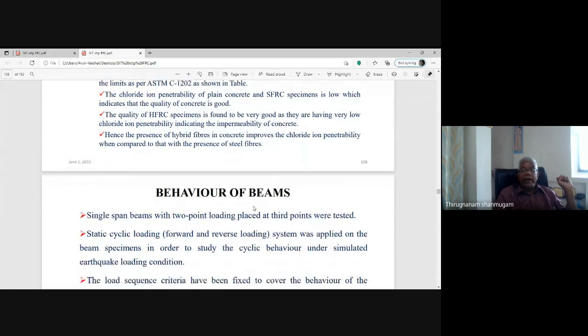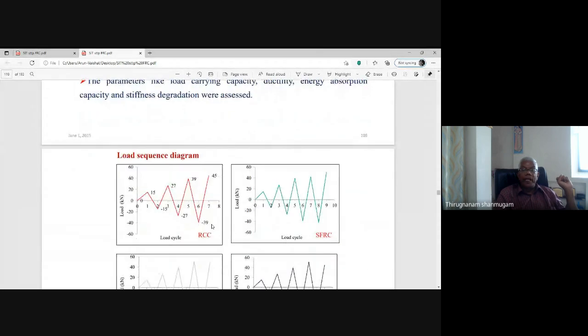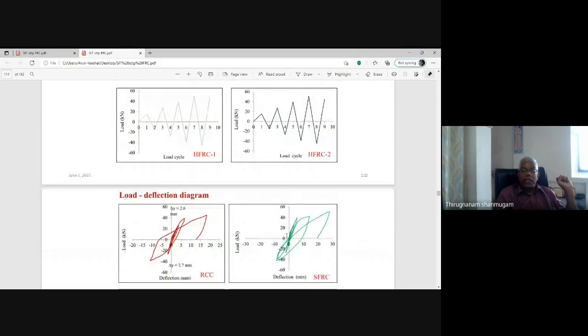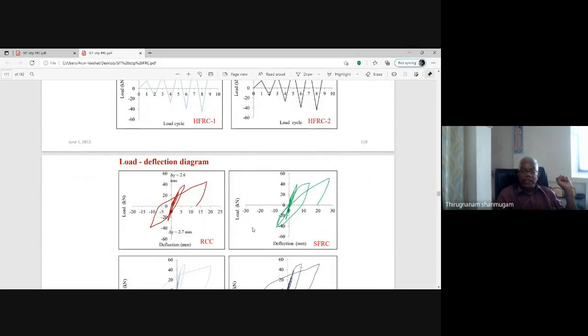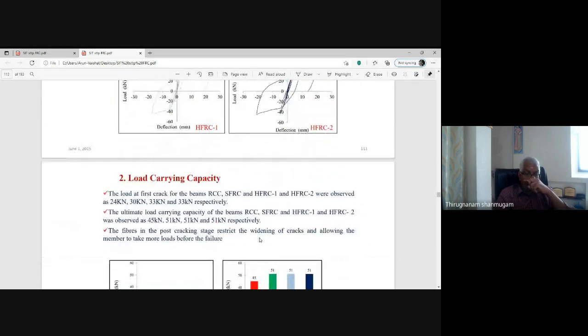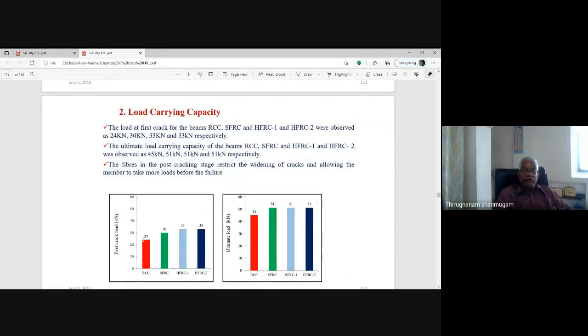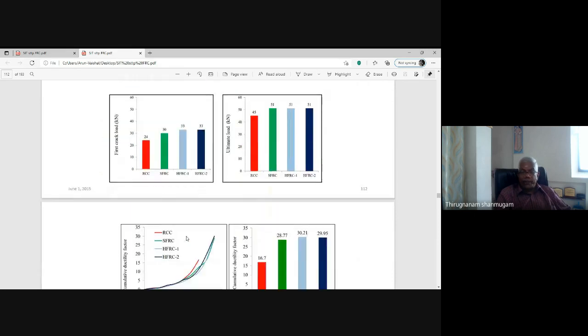Behavior for beams: reverse cyclic loading is applied, that is the loading sequence, load deflection diagrams, hysteretic load deflection diagrams. So the load carrying capacity, the first crack load, is very much increased, 24, 30, 33, 33, etc. And the ultimate load is slightly increased, 45 to 51, 51, 51, etc. Because the fibers will not contribute to the ultimate load characteristic. They contribute only to the first crack loads.